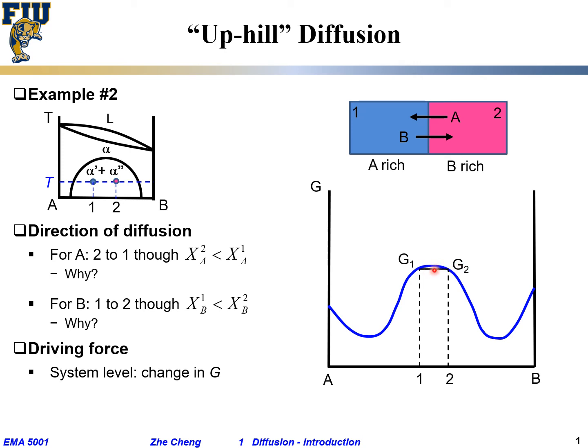The initial system Gibbs free energy lies somewhere along the tie line connecting G1 and G2 — exactly where depends on the relative amounts of each piece. If we are roughly 50/50, the system lies roughly in the middle of that tie line; that is our initial system Gibbs free energy. At equilibrium, the system reaches a minimum Gibbs free energy lying on the so-called common tangent line, because we are in the two-phase region.